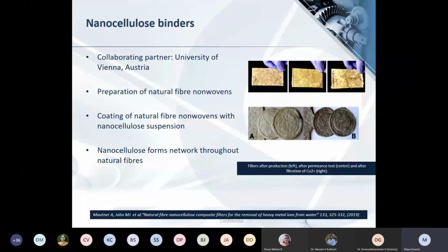This is another example of a project where we use nanocellulose, and our collaborating partner was University of Vienna in Austria. And here we use nanocellulose as a binder. First step was to prepare natural fiber nonwovens, which we did in our nonwoven pilot plant. And I think we used agave fibers. And then these nonwovens were coated with a nanocellulose suspension, and then heated to form the solid structure that you see here.